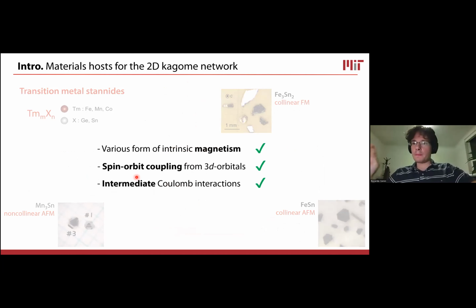And one particular aspect that is specific to this class of materials, the transition metal stannides, which sets them apart from a lot of other systems where people have been looking for interesting topological effects, is that many of these materials are magnets. And many of these are room temperature magnets. Like Fe3Sn2, which is the first material that I will tell you about, is a collinear out-of-plane ferromagnet with a Curie temperature above room temperature. They have spin-orbit coupling from 3d orbitals, which is not gigantic, but is in the order of a few tens of milli-electron volts in some cases.